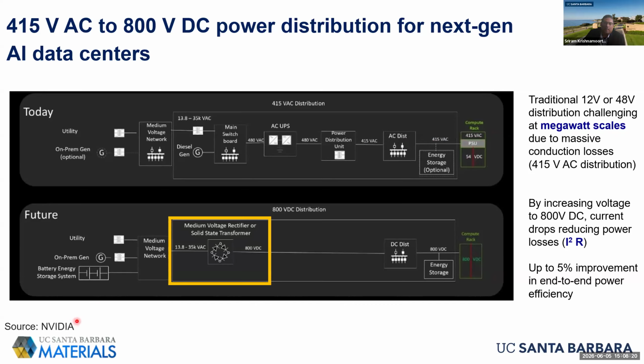This is a paper from NVIDIA where they envision a future where, by going to a much higher voltage DC distribution, going directly from 13.8 or say 35 kilovolt AC to an 800 volt DC distribution within the data center, and then taking the 800 volt distribution directly to the compute rack, and then locally doing the power conversion down to the GPUs.